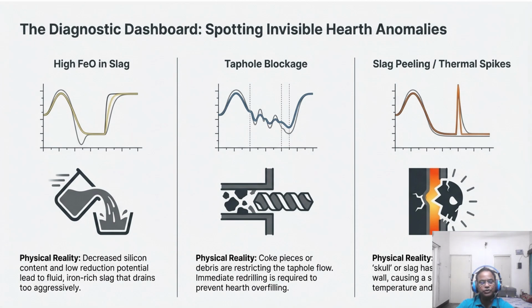stuttering signal tells you that coke pieces are causing a taphole blockage, requiring an immediate redrill or proper siphoning point adjustment after closing and again redrilling. On the right, a sudden spike indicates slag peeling, where a protective layer has fallen off, as shown here, causing a sudden shift in the conductivity.